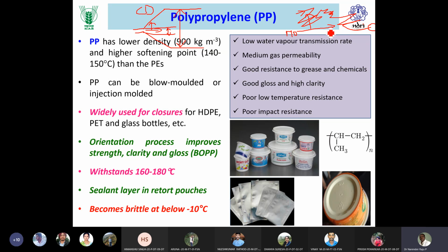The alignment of the polymer chains is now more uniform, and the thickness is reduced. This entire stretching is done near the softening point of the material. Immediately it is chilled or cooled on chill rolls to remain in this particular length.